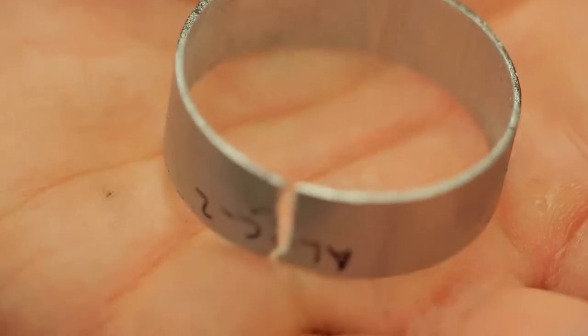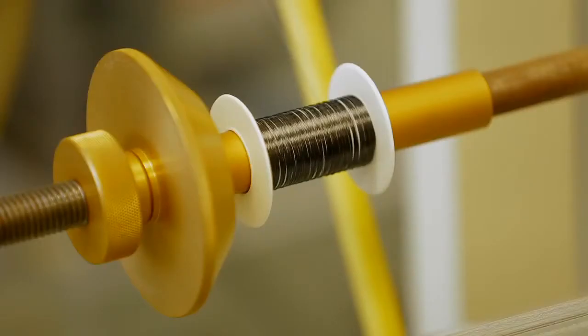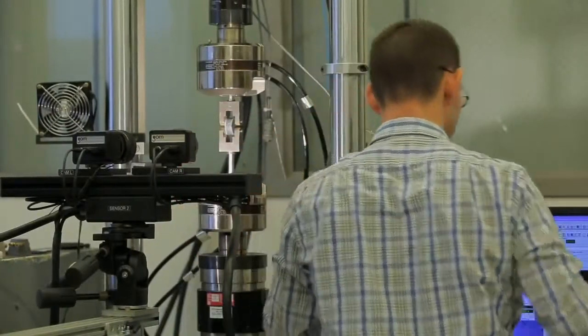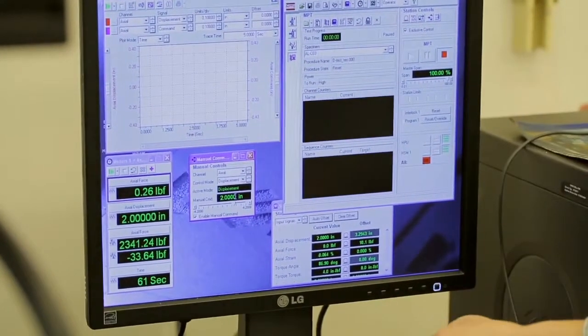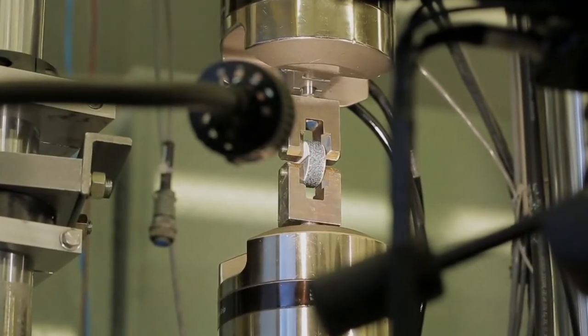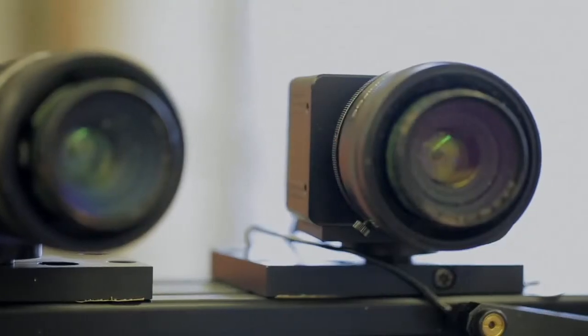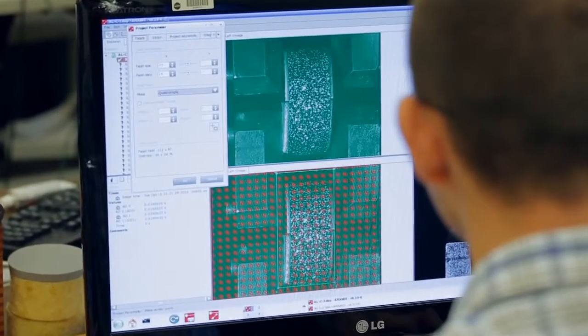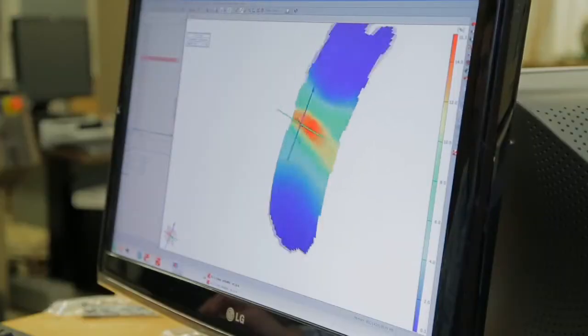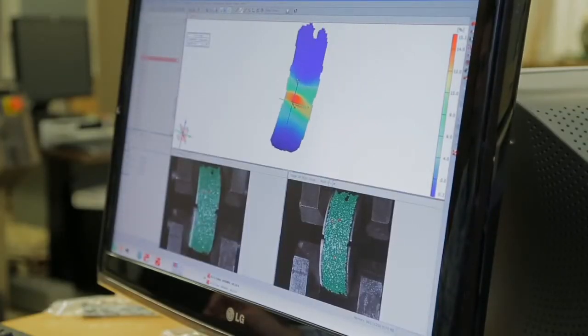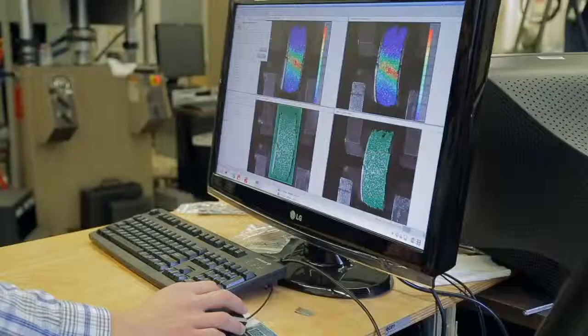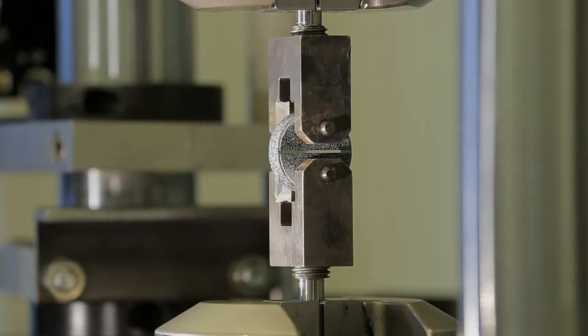Tiffany, how do you guys prepare for a carbon overwrapped pressure vessel test? So, we start off by taking the tensile strength of ring specimens, where we have an aluminum ring, and they're overwrapped with a carbon nanotube yarn and resin and a composite structure. And the reason why we do this is to help us predict the load at where our composite overwrapped material is failing. So, the rings are speckle-painted for digital imaging correlation, so we can better determine how and where the failure occurs. So, you guys actually plan in these tests to actually break the rings?